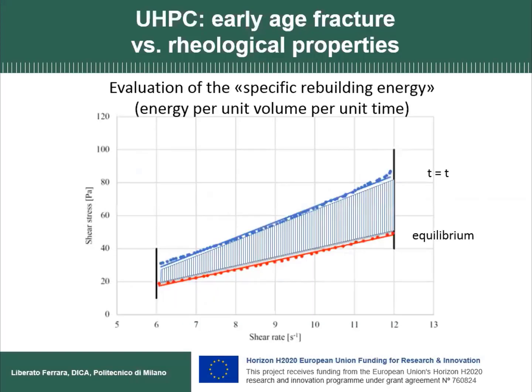And then, isolating the results between two significant shear strain rate values, superimposing the equilibrium loop and the successive descending branches, the area between these two curves is defined as specific rebuilding energy. Actually, it's an energy per unit volume and per unit time. So its dimensions are Pascal per second, that is, Pa·s^-1.